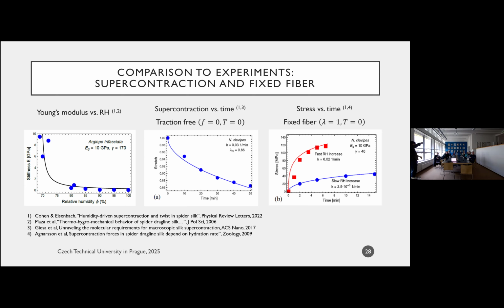So I'm holding it, it wants to contract, I'm not letting it contract, it's under tension. And now there's a stress that develops, they measured the stress. And again, they measured it at two different relative humidities, or increases of two different rates of relative humidity increase. And again, you can see we get a reasonable fit to these. But the whole reason we came up with this problem was to characterize the twist. And so the next thing is let's characterize the twist.